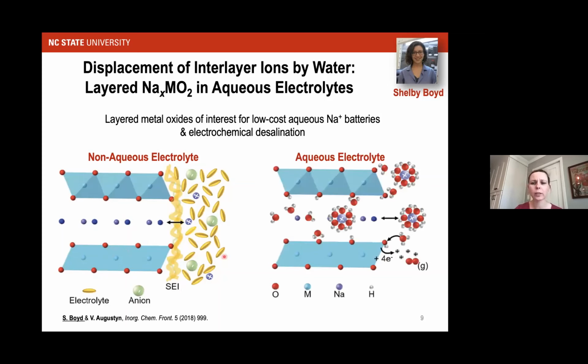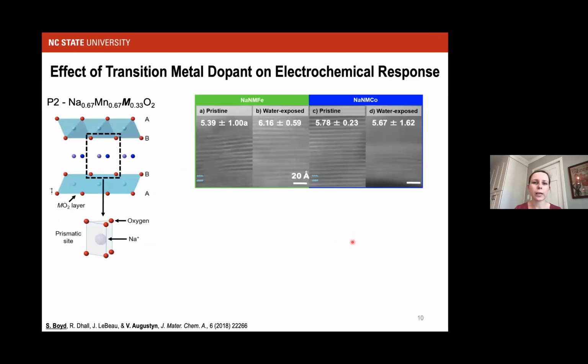But in aqueous electrolytes, you no longer have that possibility. So you don't have any solid electrolyte decomposition products. They're gaseous, right? Oxygen evolution, hydrogen evolution. And there's a very strong likelihood that your material can become hydrated because of the presence of water. So you have this very, very intimate mixing between your material and the aqueous electrolyte. And we set out to understand what goes on when we place a typical non-aqueous sodium ion electrode material, this class of P2 layered oxides, into an aqueous environment.